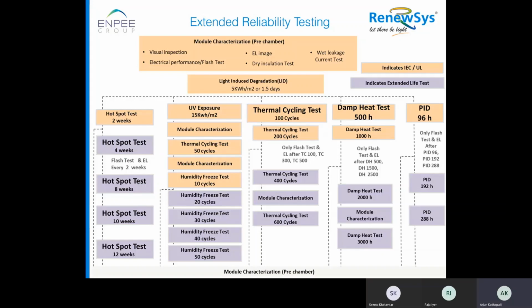Basically, we do visual inspection, followed by EL imaging, wet leakage, flash test, and dry insulation test. Once that is done, we keep the modules for light induced degradation, that is LID, at 5 kilowatt hours per square meter, which is equivalent to 1.5 sunny days. Once the modules qualify these tests, they go for hotspot.